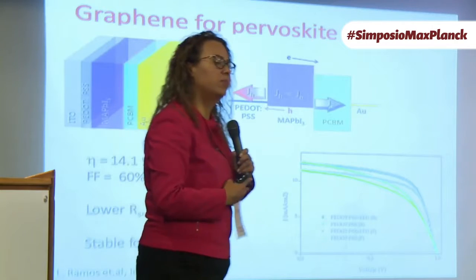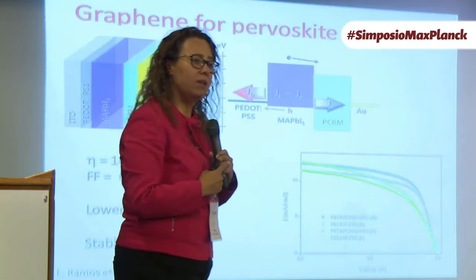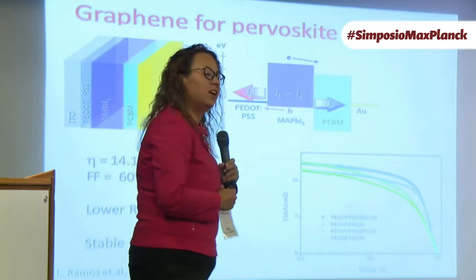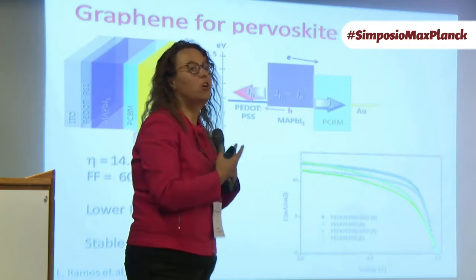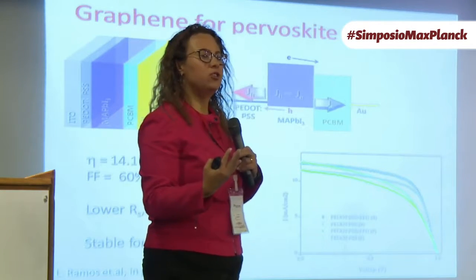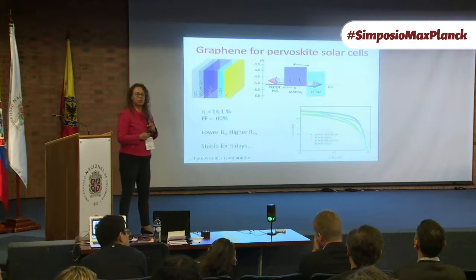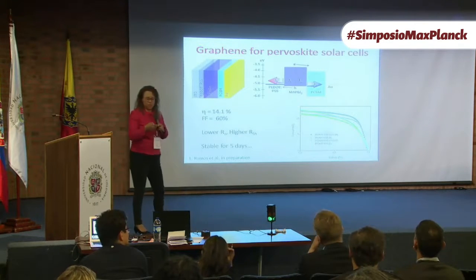The other problem is that the efficiency or stability of these solar cells is not great — they last about eight hours. So you could have 23% efficiency, but the solar cell is dead in eight hours. Since we had a group working on perovskite solar cells, we decided to put our graphene on the perovskite solar cells to see how it behaved.